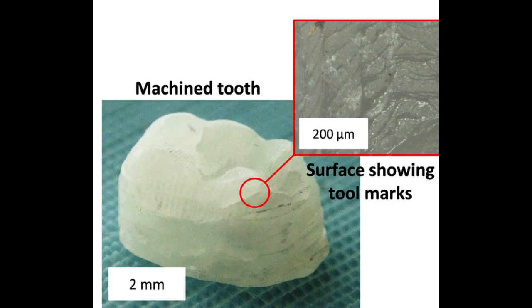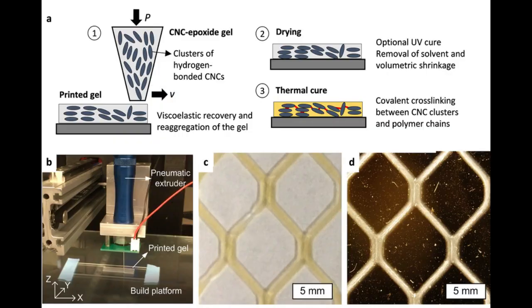The researchers looked to develop a composite with a high fraction of CNCs that they could shape into strong, durable forms. They started by mixing a solution of synthetic polymer with commercially available CNC powder. The team determined the ratio of CNC and polymer that would turn the solution into a gel with a consistency that could either be fed through the nozzle of a 3D printer or poured into a mold to be cast. They used an ultrasonic probe to break up any clumps of cellulose in the gel, making it more likely for the dispersed cellulose to form strong bonds with polymer molecules.